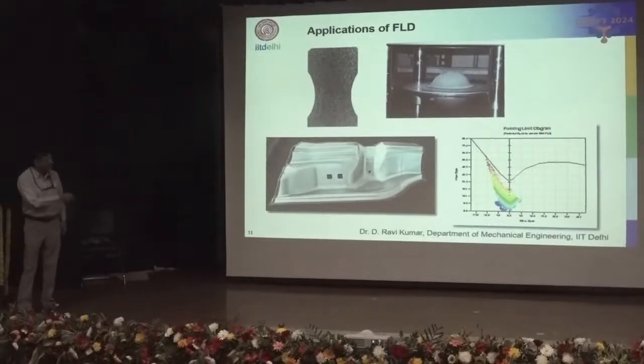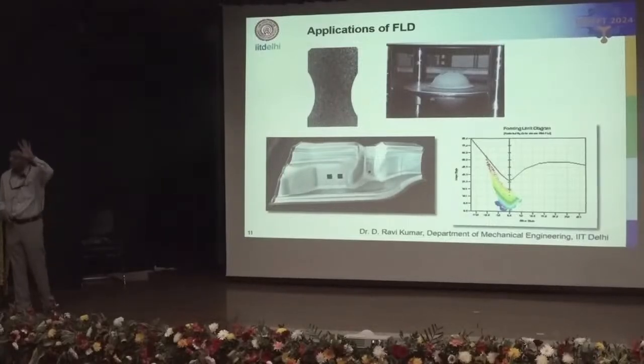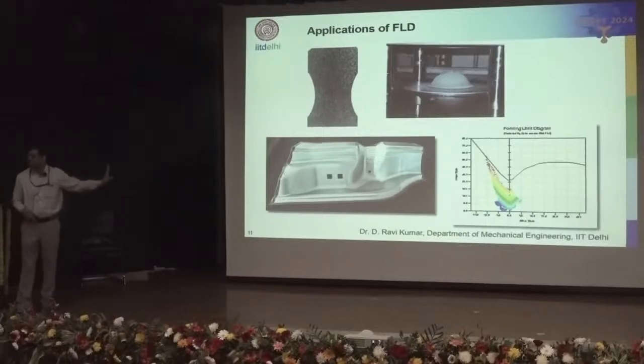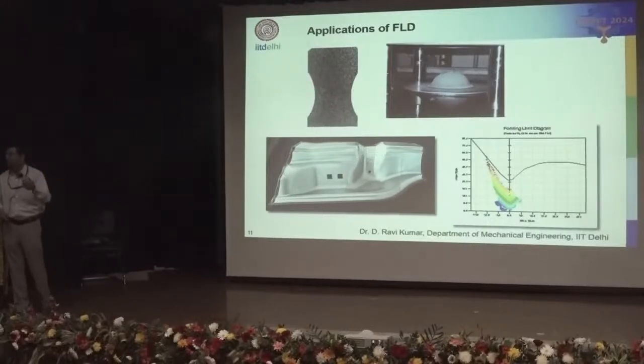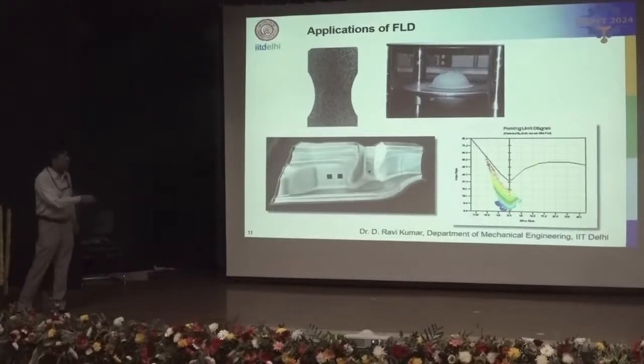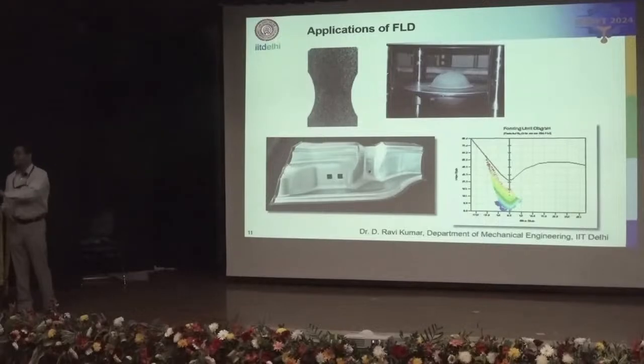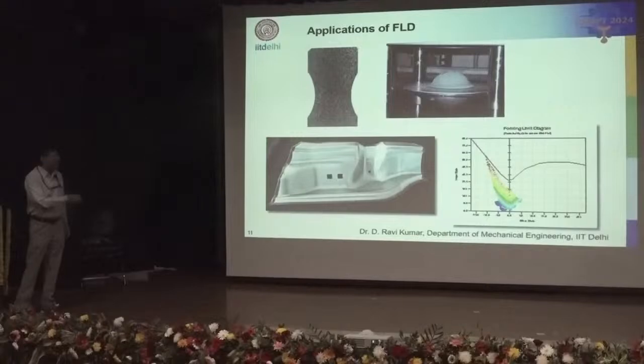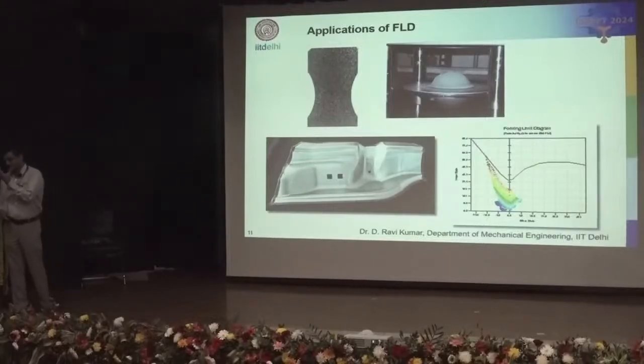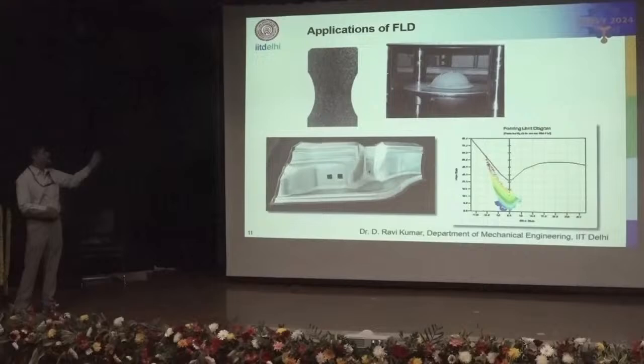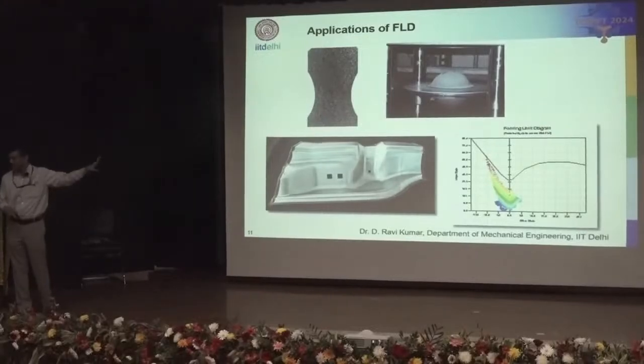So if the strains at any location are going close to the FLC or above that, it means that the operation is not going to be successful. We need to rework on either the process variables or the design variables. But if the strains on the component are well below the forming limit curve, then it means that it's a safe operation and those parameters can be implemented on the shop floor. And this is a very simple thing. For a very simple object, it is easy to measure strains and superimpose them on the FLC.